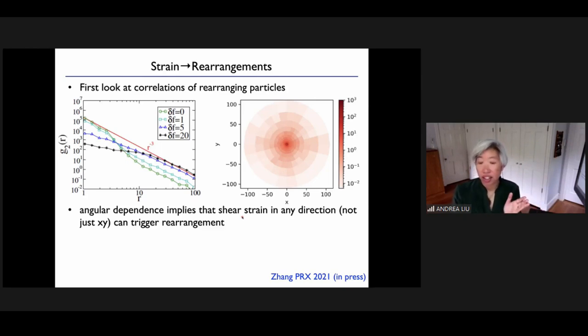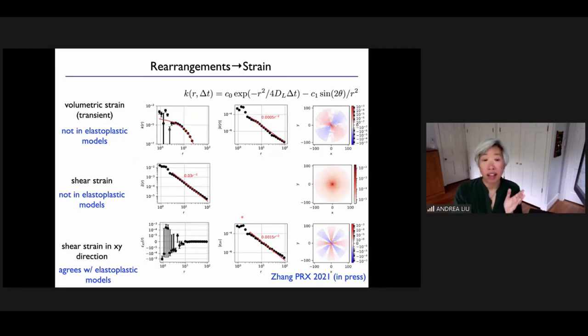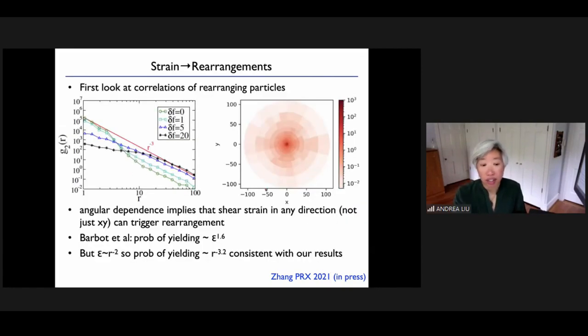And this term then should depend on the shear strain. Okay, if you remind yourself of what we found earlier, it's the deviatoric strain here, which is angularly isotropic. Okay, and that is what we're seeing in the pair correlation function for rearrangements. What about the power law? We're seeing it's not a great power law, but at large distances, it seems to be converging to something that's sort of like 1/r cubed, not great.